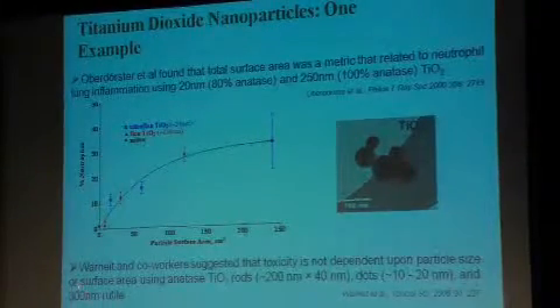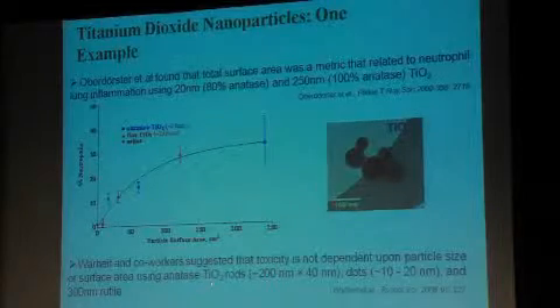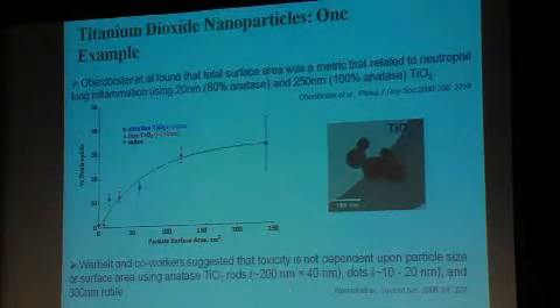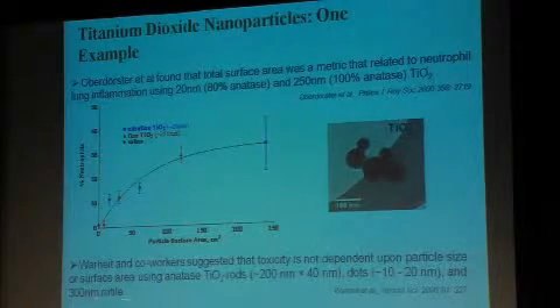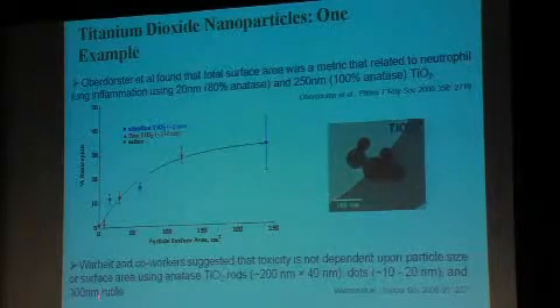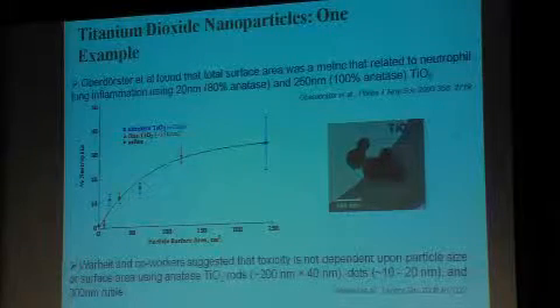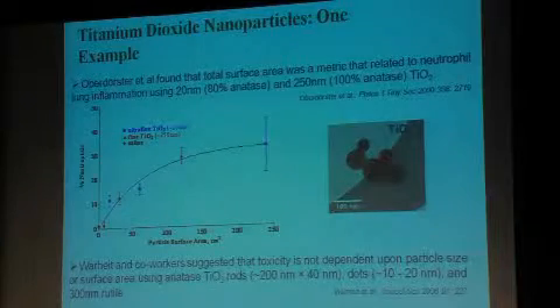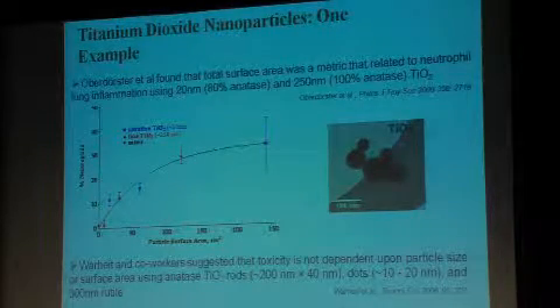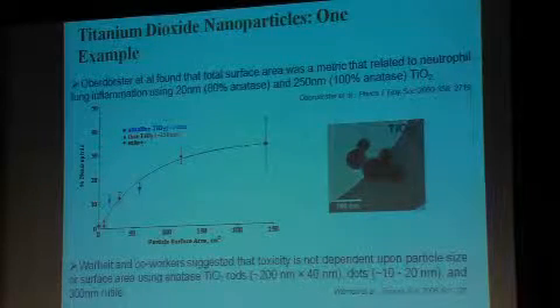But then in recent years, you see Warheit, he suggested that it's not dependent on particle size or surface area, and used a different shape of material. Again, not wrong results, but clearly different, and maybe a very limited number of samples to come up with some of these conclusions. And you can also see different crystal phases. TiO2 is a very common material. The anatase crystal phase and the rutile crystal phase itself could be very different. And then also a study by Sayes shows that you could have different effects, but again a very limited number of samples. So this need for the availability of different amounts of samples is very important, and to do these experiments well and use protocols which are common across the board so that we can duplicate some of these results before we can move along.